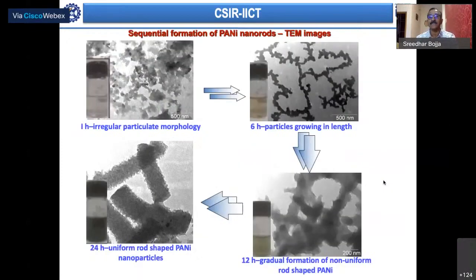Then how do they make a difference? We will try to understand that. We tried to measure their TEM images at regular intervals. At 1 hour, small dots are forming, which by about 6 hours tend to self-assemble into that kind of form. By about 12 hours, a rod-like morphology slowly begins to appear, but by 24 hours you see they are perfect rods. The color of the solution also changes from almost colorless to dark green, which is the color of polyaniline. So this polymerization is complete, and you see they are perfectly rods.